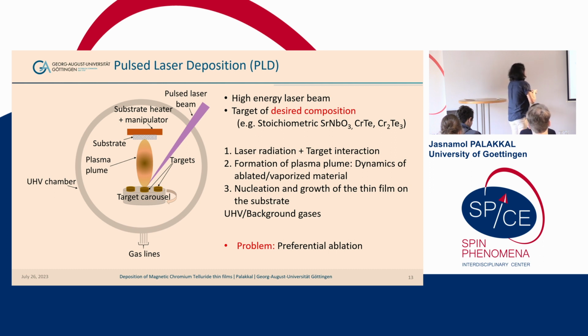But there is a problem in the case of PLD. It creates preferential ablation of the material, and sometimes the stoichiometry will not be transferred to the substrate. This is the case if you are using chalcogens like CrTe or Cr2Te3. If you use a Cr2Te3 target here, most of the time you will not get Cr2Te3 in the film. So this is a problem when you have materials with different volatility.